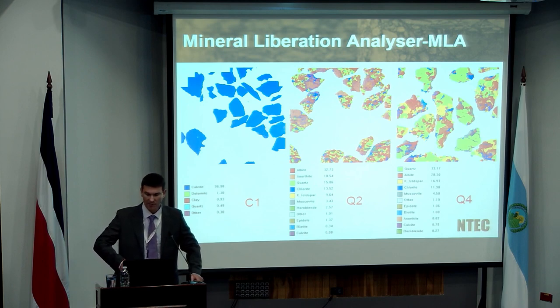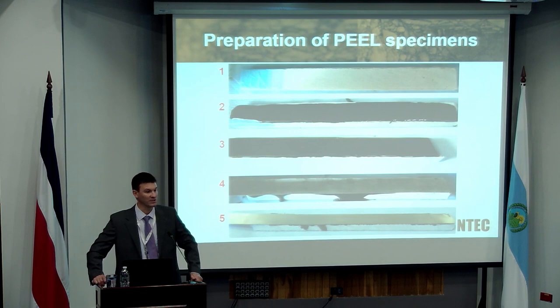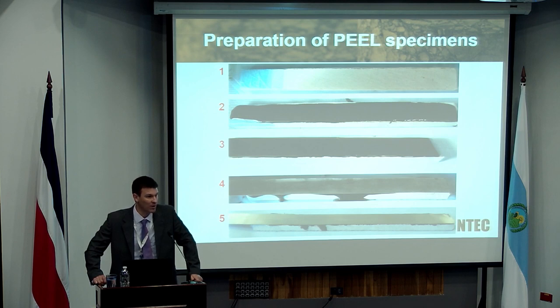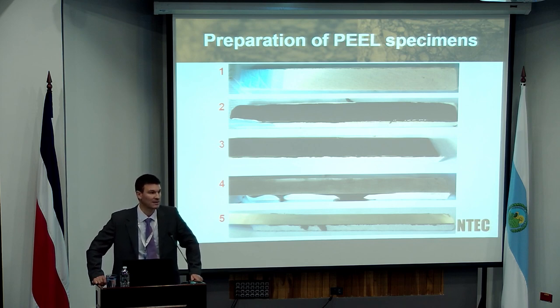So how do we go about producing specimens for the peel test? Well, it's a very simple approach. This was obviously a development stage proposal or project. This was the final outcome in terms of how we produce these peel specimens. You take your aggregate substrate, and you very, very carefully pour hot bitumen onto that substrate, making sure you control the thickness of that bitumen adhesive layer by using copper wire.